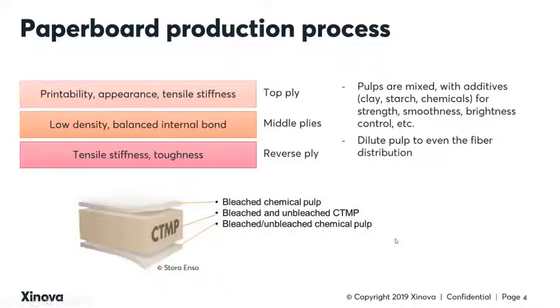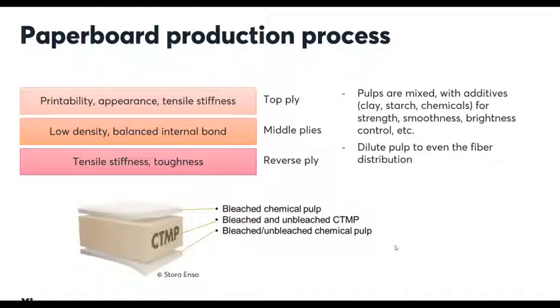We'll next take a little deeper look at this process to help understand the paperboard product which you are being asked to improve. Paperboard has several layers of pulp. These pulps are mixed, diluted, often with chemical additives added for various properties such as strength, tensile stiffness, smoothness, brightness control, and more. The top ply is the most outward facing, and so it must be smooth enough to allow for printability and a smooth appearance. The middle plies can consist of several layers depending on the application for this paperboard and include both bleached and unbleached chemithermomechanical pulp, or CTMP. The reverse ply is the innermost layer.